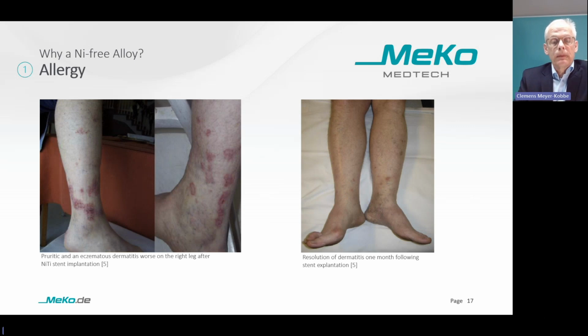A middle-aged man, a worker in a factory, was suffering from claudication in his right leg. Finally, he received a nickel titanium stent in his superficial femoral artery, so the upper leg. After a few days, a rash started in his right lower leg, below the knee. You see it here. This shows that the reaction on a nickel allergy is not always exactly at the location of the implantation. Over the time, the rash went worse. The leg showed strong dermatitis.